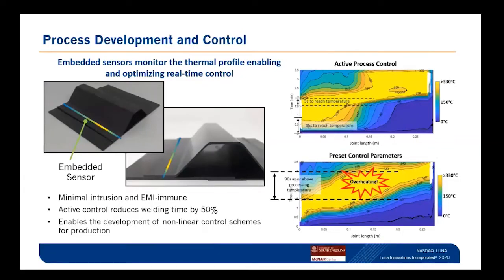I mentioned earlier I was going to go over one of the examples we've got when you're joining two pieces. In a test that we've done, thermoplastics are becoming more widely accepted due to the properties that they can be reheated multiple times without having to worry about damaging the polymer itself. We can, in this case, put a fiber in the bond line of these two parts that were being joined. And we were able to monitor the temperature within that bond line and use that as feedback control to, in this case, an induction welding head, in order to adjust the parameters so that we didn't overheat the part and cause any structural deformities, and also minimize the degree of stresses left inside the part once the joining was done, but also ensured that a good joint was made.